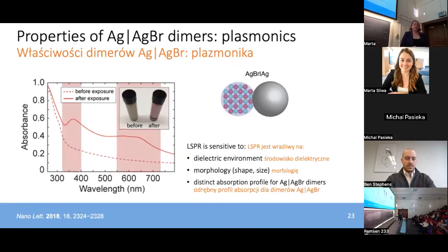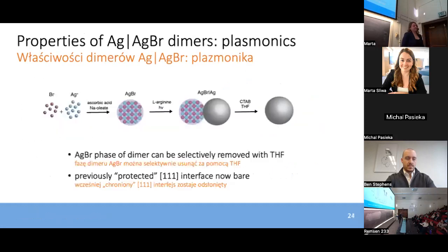But what we were interested in is determining what exactly is giving rise to these two new features in the absorbance profile for the silver-silver bromide dimers. So to do this, we wanted to determine what aspects or components of the dimer morphology are giving rise to those two new peaks. First, we focused on the interface between the silver bromide and silver phases of the dimer. We're able to isolate that interface by introducing some nucleophilic solvent and selectively digesting away that silver bromide phase to yield a single silver nanoparticle. After we etch away that silver bromide phase, the interface is now exposed.